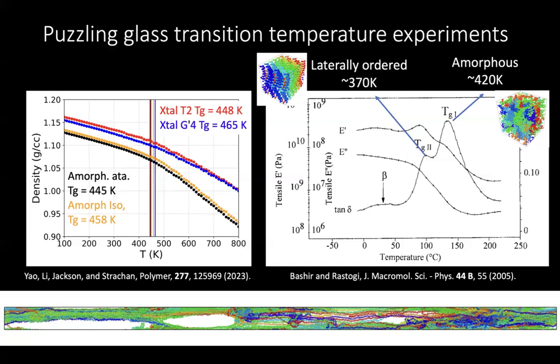And so now when you look at the relaxation dynamics of these stretched heterogeneous systems, where you have both the ordered region and the amorphous region, this part behaves just like this guy, just like our amorphous region. But the ordered region behaves nothing like the perfect ordered model that we have, because these nanovoids speed up, accelerate the mobility. So even though they're ordered, they have very fast relaxation. They have a very low glass transition temperature.